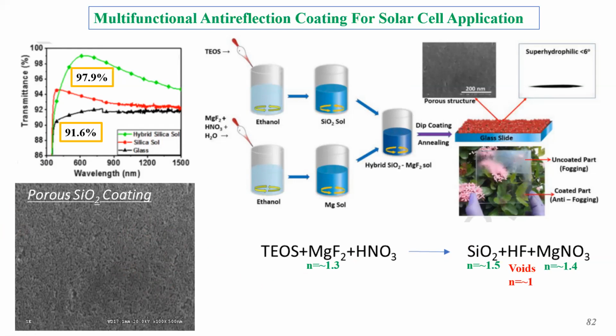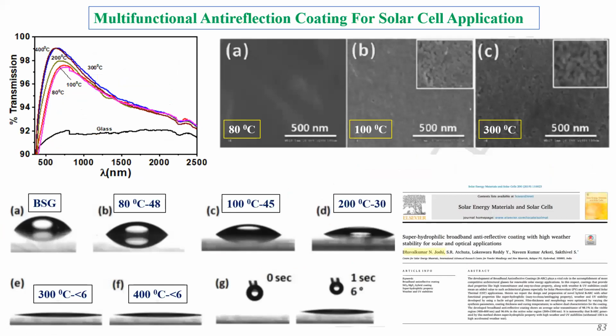So this was really excellent work, and we were about to patent it, but we could not synthesize this material on a large scale. When we want to patent it, we should at least be able to make 1 liter of solution in one go. But this synthesis procedure does not work every time, so we could make only 25 ml of solution. So we just published this work in Solar Energy Materials and Solar Cells. This is a really good, high impact factor journal.